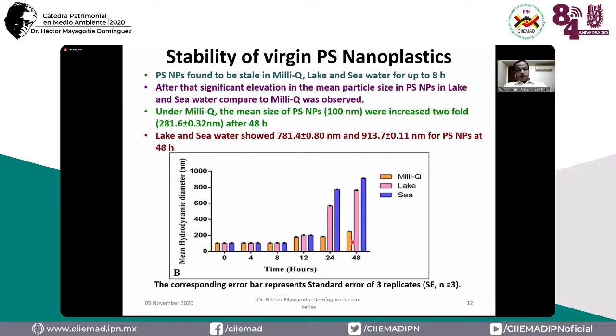So there could be two possibilities. One is that the colloids in the seawater and the lake water would add up to the particle size, or it is the aggregation of these nanopolystyrene, they aggregate together and become a bigger particle size. So if polystyrene combined with the natural colloids in the water matrix, then there is a 100% possibility that it could be engulfed by a living organism, because the organism will sense it as real food, and the particle will get into the system.